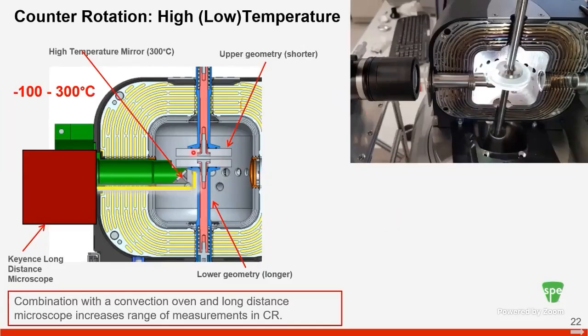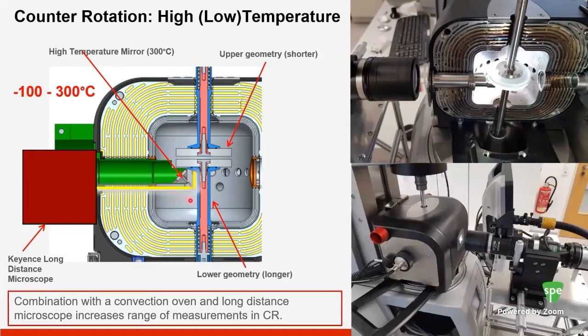Now, we have done some recent modifications to the setup where you can actually go to higher temperatures. Remember, the measurements I talked about earlier were all at room temperature. But one can use a convection temperature device, shown here, which is a CT600, and use a long distance microscope objective coupled to the oven, through this tube shown in green, which also houses this high temperature mirror, as you can see. You can reach elevated temperatures up to 300 degrees.